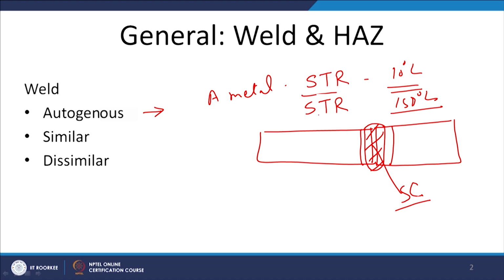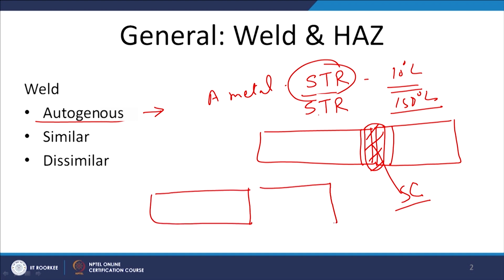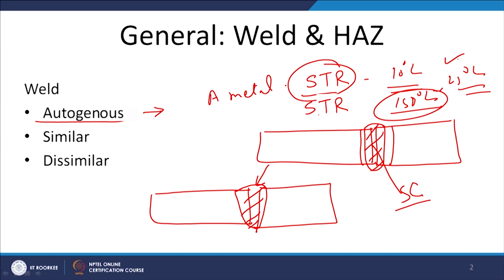So, in order to avoid the weldability issues related with the higher solidification temperature range, sometimes autogeneous welding is avoided and we try to weld the base metal using a suitable filler, so that the solidification temperature range can be reduced, say from 150 to 25 degrees centigrade. In that case, the solidification cracking tendency will be reduced because of the reduction in the solidification temperature range. The mechanism of solidification cracking I will be talking about subsequently, but what I am saying is